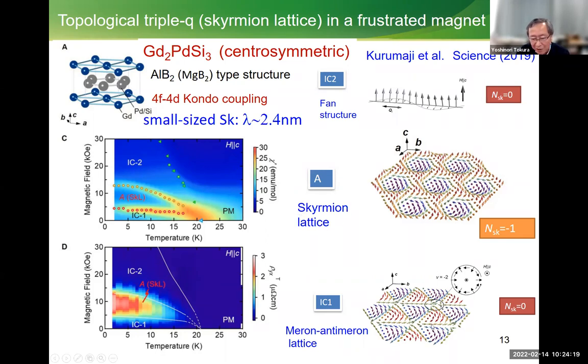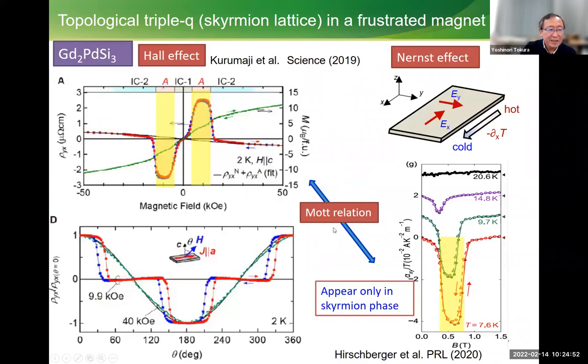But this is also triple Q, and here no emergent magnetic field is produced, so we anticipate it's a so-called meron, anti-meron structure. It's a very close relative between the skyrmion and the meron crystals. But one is non-topological, the topological charge is zero, while this is a topological unity. The fact is that we observe the very large anomalous Hall effect only around this skyrmion lattice region. And this is the example.